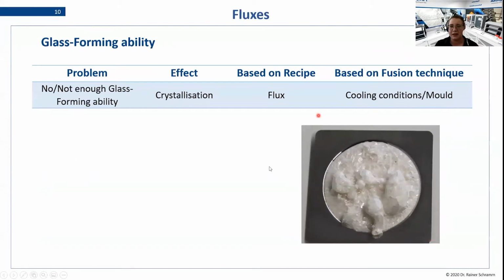Maybe you already saw something like this when you are talking about fusion, and if you're doing fusion in your lab. What is this? This is a crystallized bead. How does this happen? We don't have enough glass forming ability in our flux, for example. This would be then based on recipe. As well, there might be something wrong with your cooling conditions, or you might have a scratch in your mold. So there's also a way to tackle this problem based on the fusion technique. Always keep that in mind, that it might also happen due to something that is going wrong in your fusion technique. So cooling conditions, very important part, and also the mold should have a nice surface.